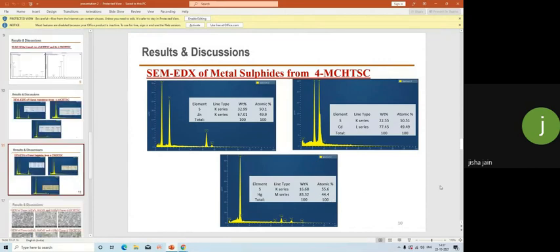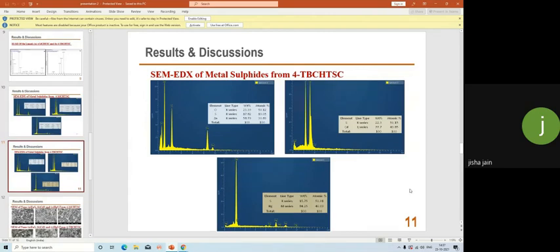And in the case of mercury sulfide, a metal deficiency defect is seen in the crystal lattice. In the case of the metal sulfides from tertiary butyl cyclohexanone thiosemicarbazone, in the crystal structure there is a large amount of oxygen seen. That is because of the presence of a large amount of capping agent in the crystal structure. And the ratio of sulfur is also very low compared to zinc. A deficiency in sulfur has occurred in the crystal structure.